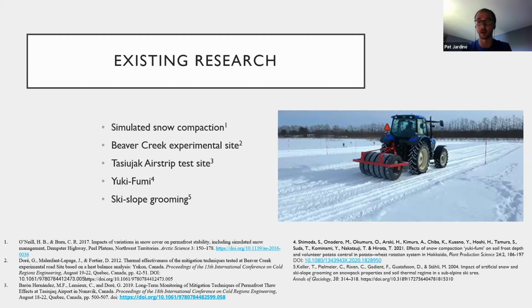I found a paper talking about how groomed ski slopes experience significantly colder temperatures on average. And I found a research study that was aimed at confirming this. They measured the density, thermal conductivity, and depth of the snow. And they found that they're all significantly modified by compaction, but there wasn't actually much of a difference in ground temperatures. This was partially because air temperatures through the winter were only just below 0 degrees, so there wasn't much of a temperature gradient, not much that compacting the snow would do. And also because there is more snow constantly being piled on the ski slopes, and that partially counteracted the effects of compaction.